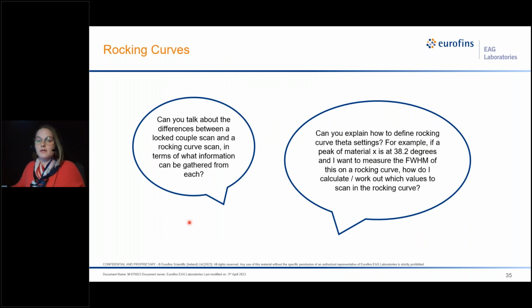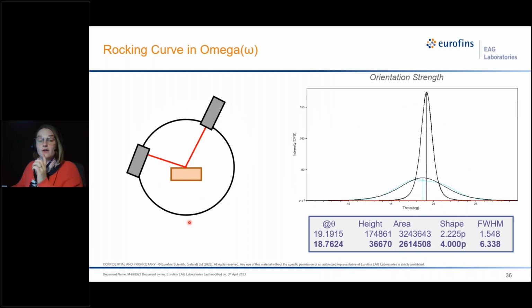Rocking curves can also give you a lot of information about texture. So for example, if you have a material X that has a 2 theta peak at 38.2 degrees, and you want to measure a rocking curve, what you're going to do is fix your 2 theta, and you're going to scan omega. We're going to scan over half, because omega should be half of your 2 theta. So in the case of 38, you're going to be scanning somewhere around the range of plus or minus 2 around the, I believe, 19 area.